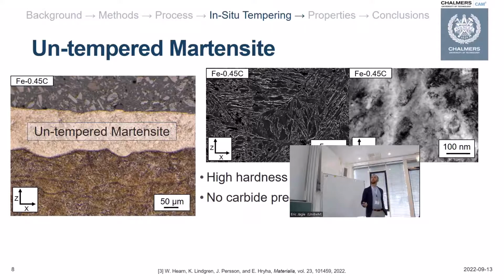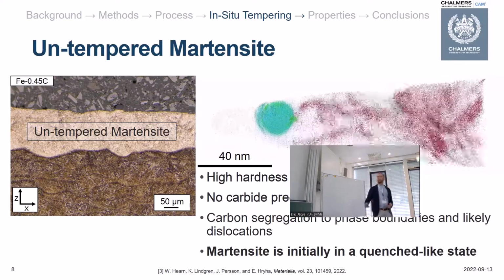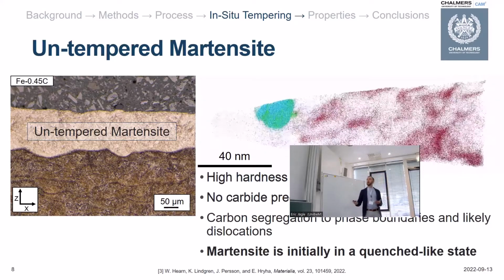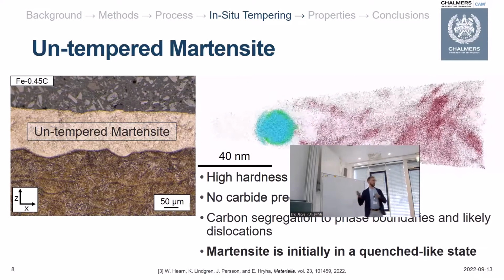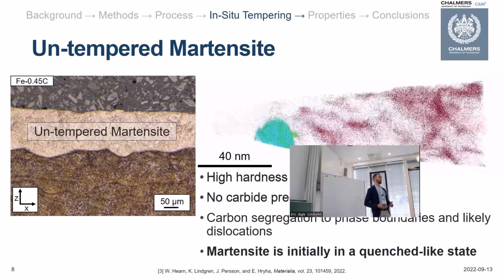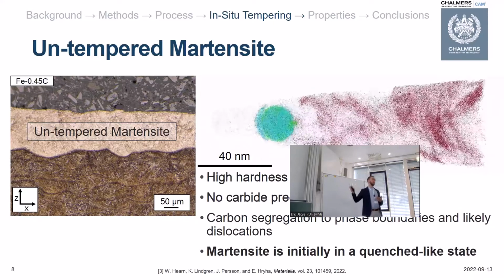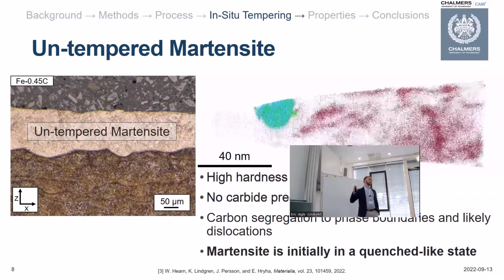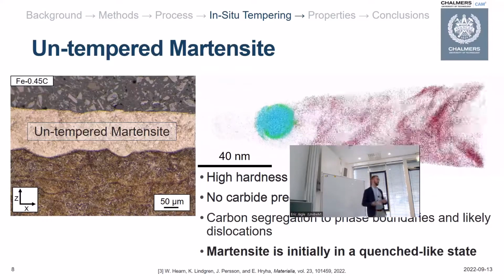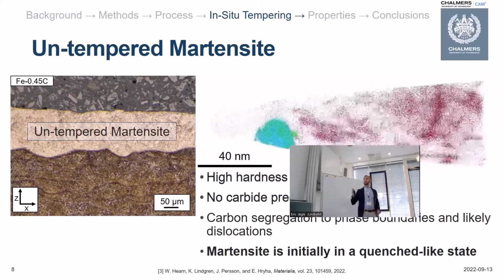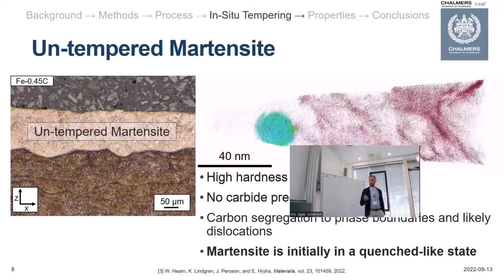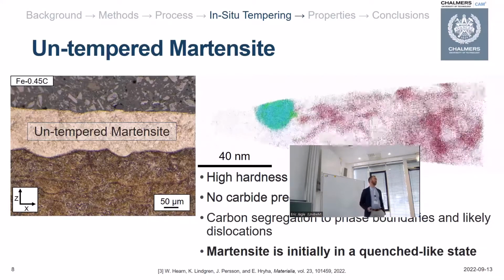We then started looking in both SEM and TEM, and what we see is a very fine lath martensite structure, but there's no clear presence of any precipitates. We then did further work with atom probe tomography, and as we saw with SEM and TEM, you do have carbon atoms, and they're somewhat segregated to specific regions in your material, like phase boundaries and dislocations, but there's no formation of any carbides. So what you see in the process is that, as you would expect, your martensite is in a quenched state where there's some segregation of carbon to different boundaries. And I'll very quickly say that if you're wondering what this is, it's just metal oxide.